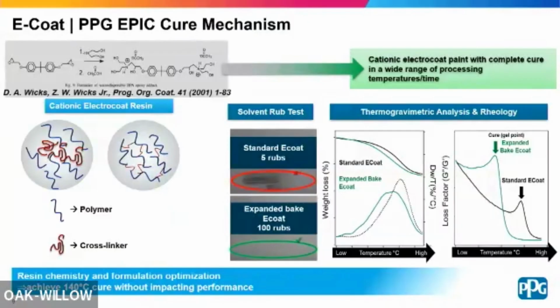So to do this, we have to start looking at blocking agents, how they're blocked, when they're released, what temperature are they going to be released at, and then how do they orient themselves quickly. So once you're able to optimize your cross-linker to your polymer, you're able to do your cure test. Now, because we all started in the lab, the easiest way to do this is just solvent rubs. You just sit there and you rub it, and you're like, hey, I've got the cure that I want. But the more scientific way to do it, and to really understand that the resin is doing what you want it to do, we look at rheology and we look at TGA.